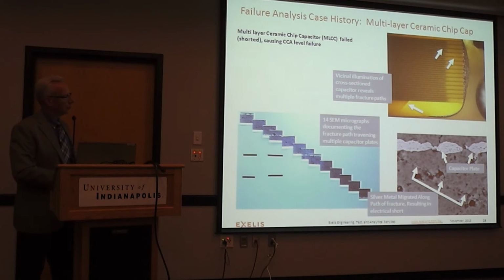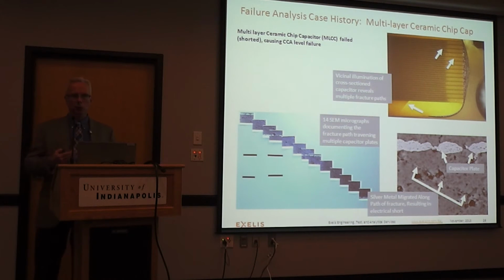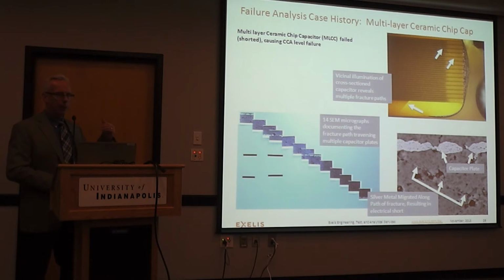That fracture path provided then an opportunity, a path for electromigration. So this SEM image down here, scanning electron microscope image, is a fracture path that's going diagonally from one plate in the cap to the other. And those adjacent plates are of different potentials. One's going to be at a positive, one's going to be at a negative. When you have a DC potential, that gives you an opportunity for electromigration along that path within that dielectric.